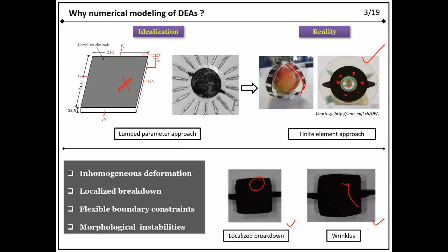Okay, so we are going to apply an increasing potential difference, and at a certain point there will be a dielectric breakdown. The system will fail. Now you cannot actuate. If you apply any potential difference, there will be no actuation, because we have a short circuit here, you can say. The modeling of such phenomena will also require a computationally efficient finite element method.